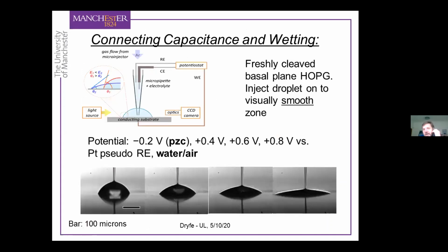So if I move on slightly, going back to the basal plane, we can connect the capacitance data that I talked about with the wetting data that I talked about. If I return to this configuration that I've already mentioned, which is when you have a droplet of electrolyte solution and you inject it onto basal plane graphite. So here's the droplet, here's the basal plane graphite, and the reason for the reflection is because the basal plane is acting as a mirror. So this is just a mirror reflecting what you have here, the droplet and the pipette where the liquid was